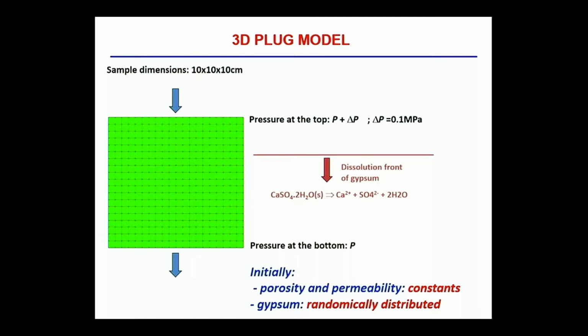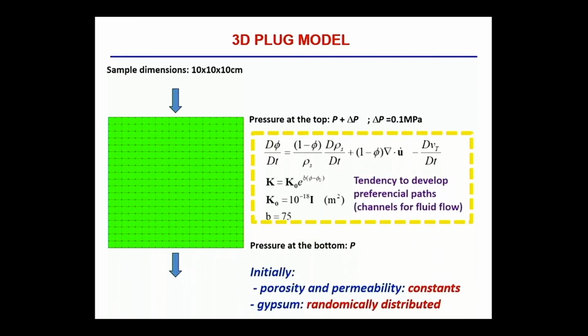We did this simulation with a sample with initially constant porosity and permeability, and a mineral that is randomly distributed. We consider a law for porosity as a function of these variables, including the total volume of minerals, and we use this experimental law with this B parameter. This B parameter is the rate of change of permeability as a function of porosity, and this is a very important parameter. Depending on this parameter, we have the wormhole or not. So the impact of the mineral dissolution on permeability is another key parameter that can affect this behavior.